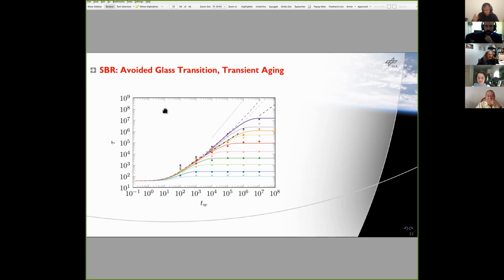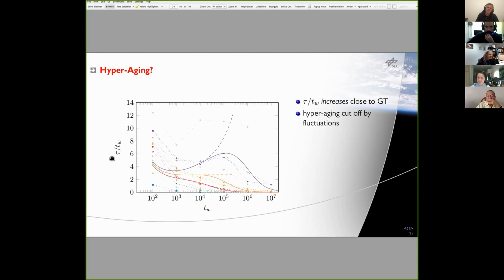But I think maybe it is. And the way to see this should be by checking whether somewhere in here we still have a superlinear growth of the relaxation time. And of course, what we can do is divide the relaxation time by the waiting time. And then if we get something that grows as a function of waiting time, this indicates a superlinear growth of the structural relaxation time. So this is what I've done here. This is the structural relaxation time divided by TW as a function of TW.